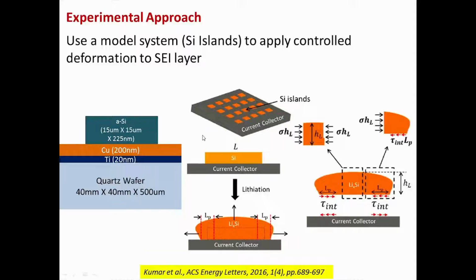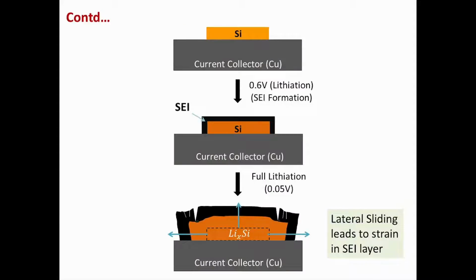During lithiation and delithiation, these islands go through huge volume expansion and contraction. What you can see now is that there is a lateral stretching of the silicon while it is expanding. So if any layer is on top of this silicon island, it will feel that stretch. So we are applying some kind of strain to the SEI layer and trying to see how the SEI layer behaves under these mechanical strains. This is our experimental approach, and it would be more clear on the next slide.